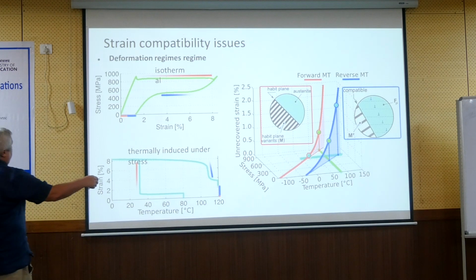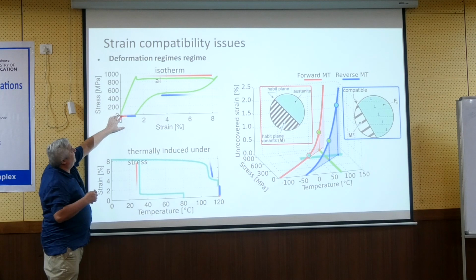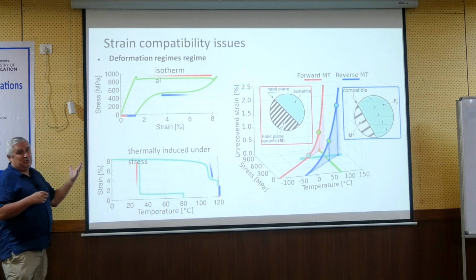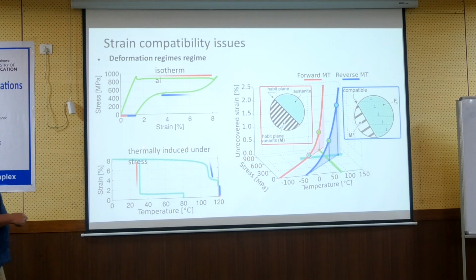If it would be at room temperature, the unrecovered strain would be here. You would not see it, but it will be there. So I wanted to show that it is here, and the same with high stress here. And so, like I said, we are striving for NiTinol which can be used at high temperatures, and we want to shift the Af temperature higher. It helps a little bit, because if you have higher Af temperature, you might have superelasticity at 100 Celsius at lower stresses. In that case, it helps, but this problem with plasticity accompanying transformation remains.